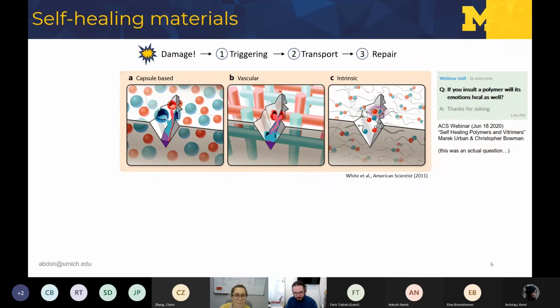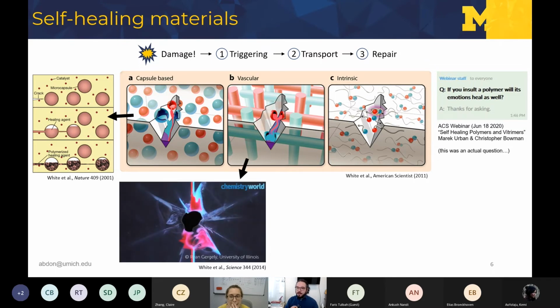So as a brief intro, we can categorize self-healing materials, especially polymer-based self-healing materials, into two main categories: extrinsic healing that relies on the addition of an external component, that can be some catalyst, some healing agents, some fresh monomers, etc., whether embedded in a capsule form or fed through a vascularized system. These have some pros and cons, of course. It's good because they're very autonomous. Once you have some damage, these capsules or vascular networks are broken, the healing agent is released, and it doesn't require an external stimulus. There are some limitations, for example, the cycling, the number of times that you can heal this material is limited,